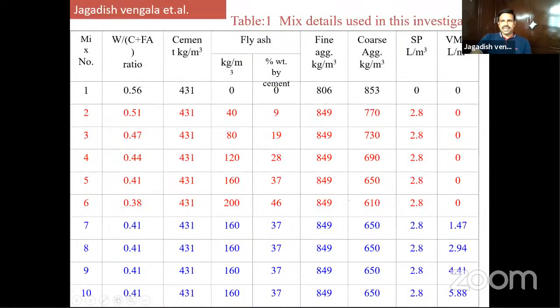These are some of the initial mixes I did. Cement is around 430 kgs. And you can see the coarse aggregate content is lower than the fine aggregate: 650 is coarse aggregate and 840 is fine. And the bottom 4 mixes, that is SCC. We arrived from a normal mix to SCC. And the fly ash we used is around 160 kgs.